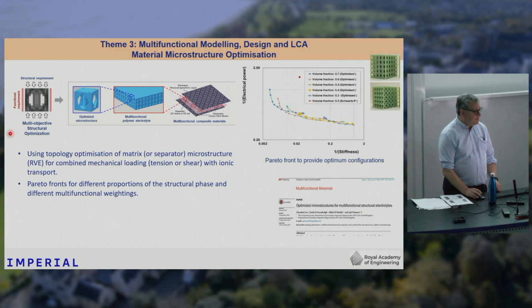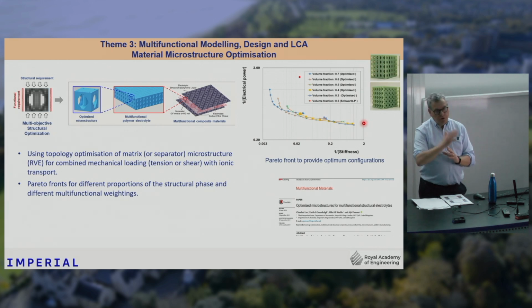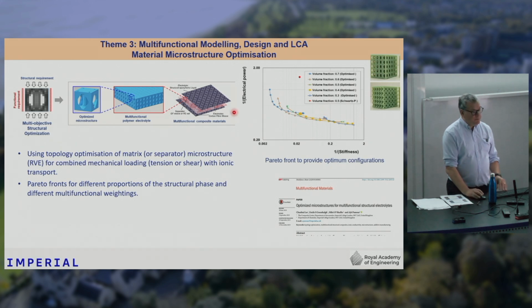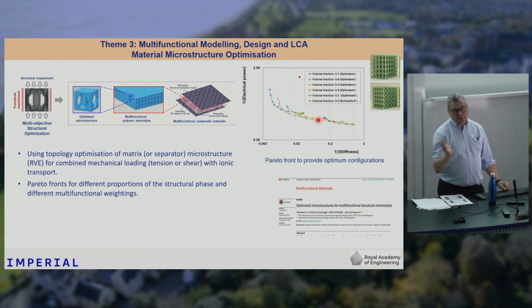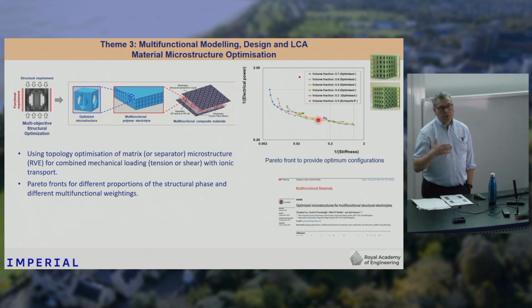The way we did this was to look at different volume fractions of those two phases, the ionic phase and the structural phase, but also different weight fractions in terms of the functions. And we plotted this as a Pareto front, where we've done the reciprocal of each of those parameters. So this end is showing you high electrical ionic conductivity. This end is showing you high mechanical properties. And so we've got this Pareto front, which is showing these are the solutions that give us, for a particular weighting between those two functions, the optimum solution, the lowest weight solution.